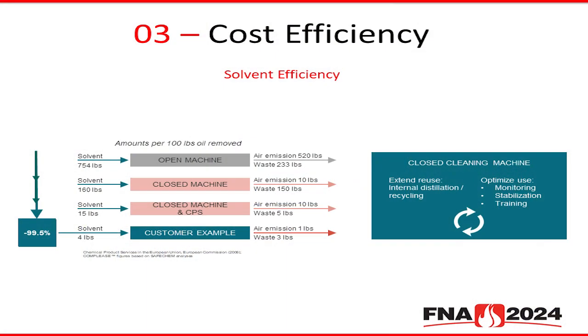We do also have some of our own customer examples where we could even reduce it further with on-site consultancy to an equivalent of 4 pounds of solvent used per 100 pounds of oil. And that is a reduction compared to the previous technology in the old days of 99.5%. And that's really something that you don't find a lot in the industry when you talk about sustainability, environmental friendliness, and chemical consumption, and how to reduce costs.